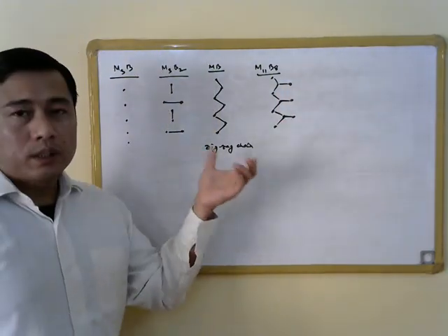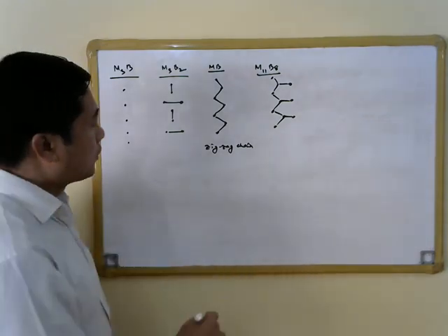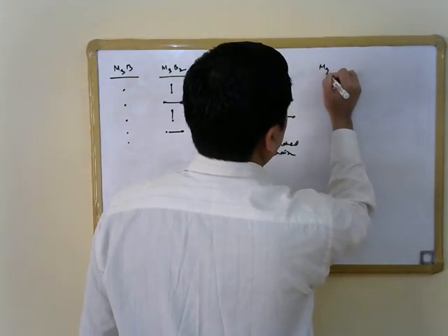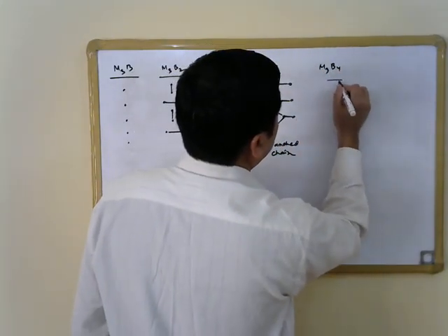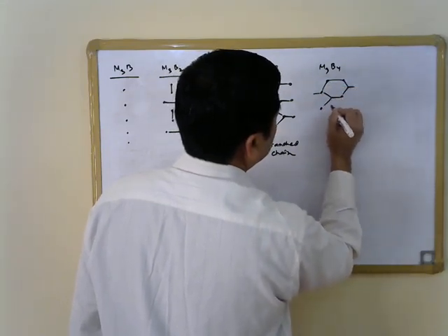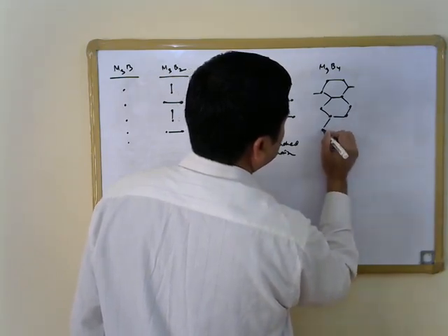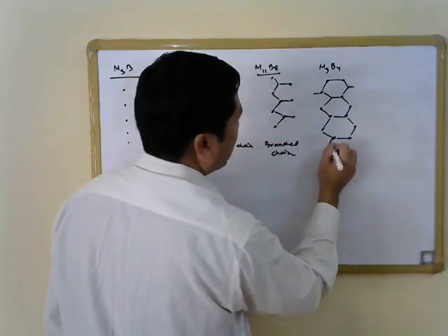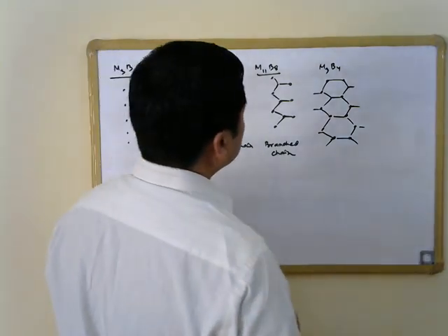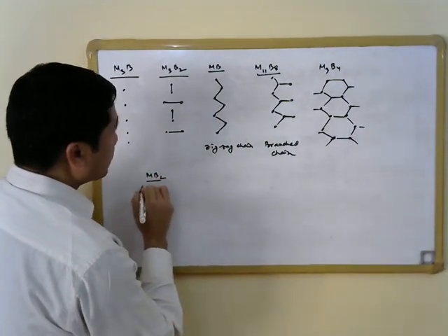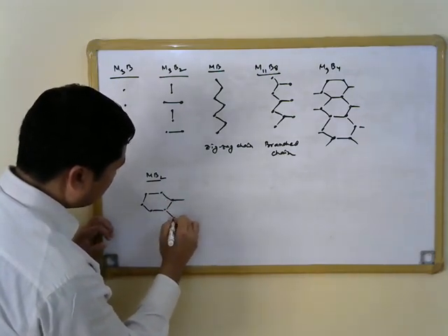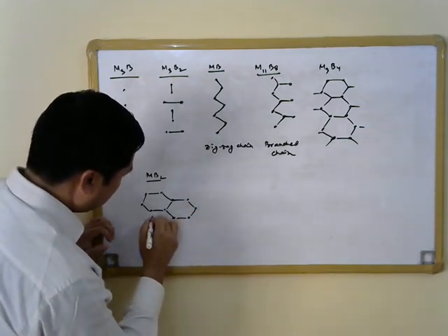This sort of branched chains of boron atoms appear, and then in M3B4 we have the chains, essentially the branch chains closes, and what we have is an array of hexagons formed by boron atoms present in case of M3B4, while in case of MB2 we have a two-dimensional network of boron atoms formed in this way.